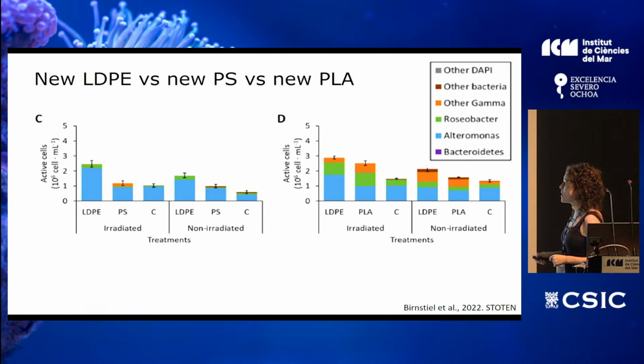So we have here two different experiments that we couldn't do at the same time because of the logistics. And so we always use LDPE as a standard that was used in both. And then we use polystyrene in this case, and here PLA, the biodegradable. We have the irradiated, the non-irradiated, and here the number of active cells.